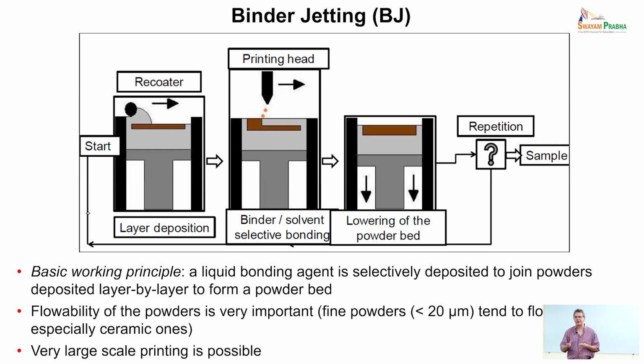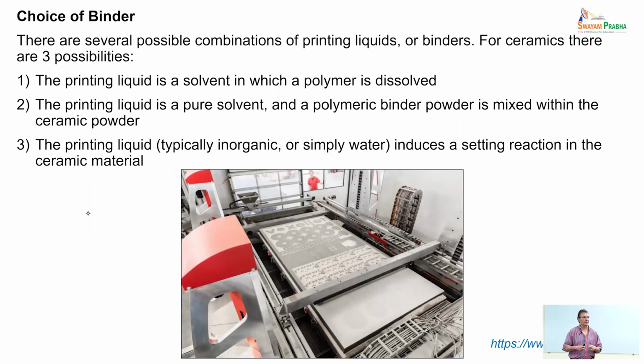And the second problem is that you may say you would like to have a part that has not just the design porosity, but also residual porosity within the solid. But then typically you want to reach certain volumes of porosity that are suitable for specific applications, and there are not many ways of modifying the porosity in the solid that comes from the characteristics of that technology. Certainly, binder jetting has strong advantages because you can do very large scale printing. You can see the person there. So this is a 4 meters by 2 meters type of bed, which is very, very good. And people use that for making, for instance, casting molds.